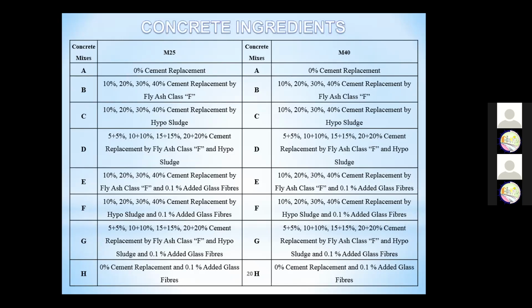the national highway. So the standard mix is concrete A with 0% cement replacement, B is 10, 20, 30, 40% cement replacement by fly ash class F. Same way, C is regarding the hypo sludge. Then D, regarding the 5+5%, is a hybrid mix of fly ash class F and hypo sludge.